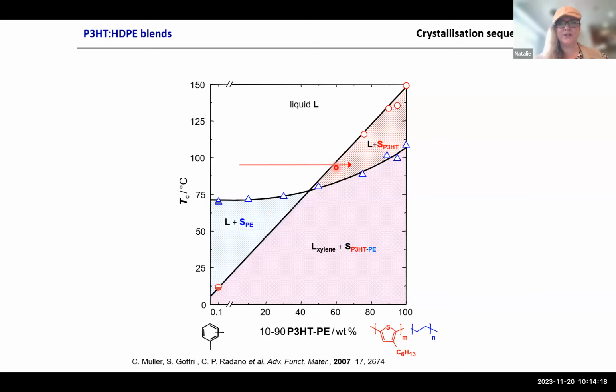So this has multiple advantages. The P3HT can crystallize where it still has a lot of mobility, so molecular mobility now, not electronic, so high diffusion, because most of the polyethylene is still liquid. That helps the ordering.